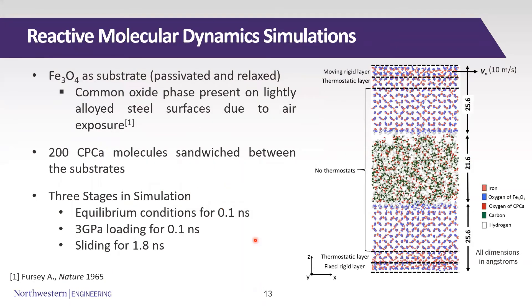Complementing the experimental investigations, we conducted reactive molecular dynamics simulations to gain further confidence in the findings and to reveal atomistic pathways followed by the lubricant additive. To replicate the tribological setup, we used Fe₃O₄ substrates — since any steel surface always has an oxide layer — and sandwiched 200 CPCA molecules between two substrates. The simulation was conducted in three stages: equilibrium conditions for 0.1 nanoseconds, normal loading of 3 gigapascals for another 0.1 nanoseconds, and then sliding for 1.8 nanoseconds, where the top substrate slides at 10 meters per second while the bottom remains fixed.